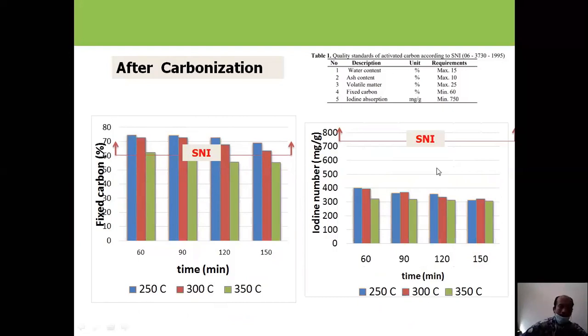The problem is arising from the iodine number. All of the treatments here for carbonization do not fulfill the value for activated carbon. So it is not activated carbon yet. So we need to do activation for making this carbon activated and can be used later for adsorption.